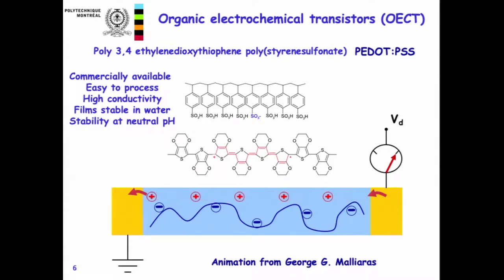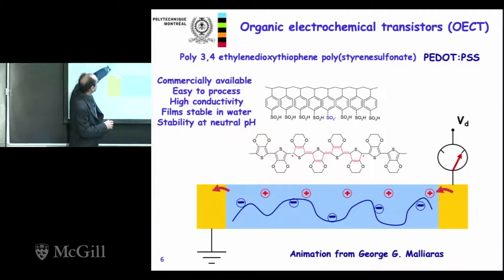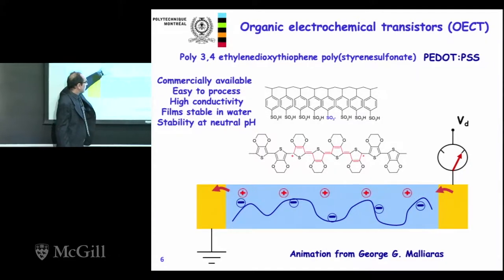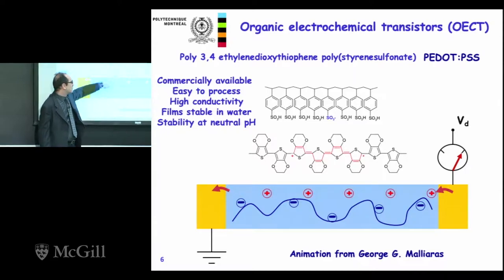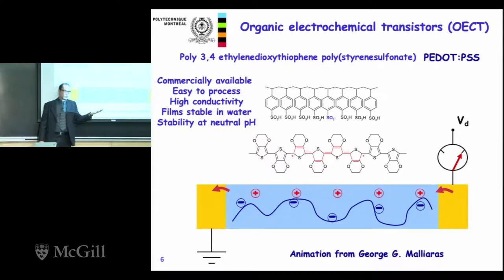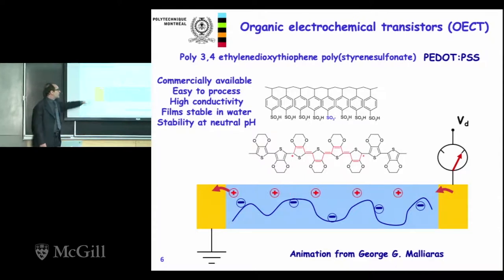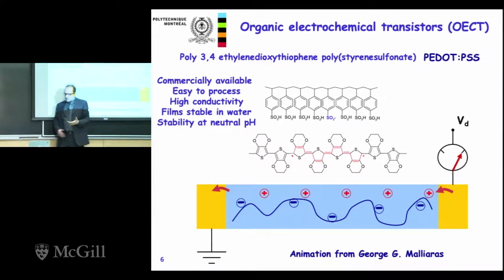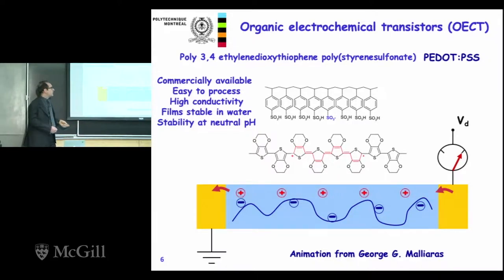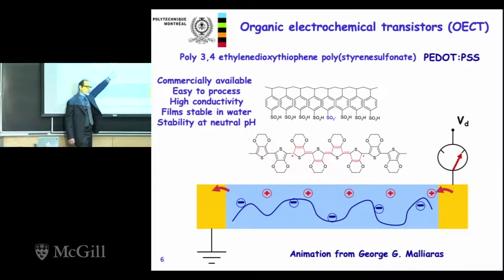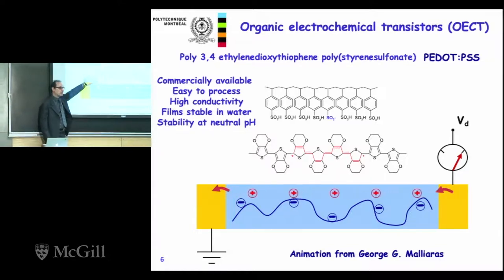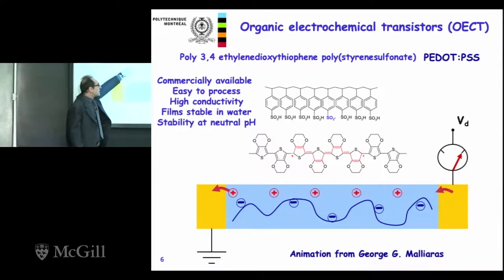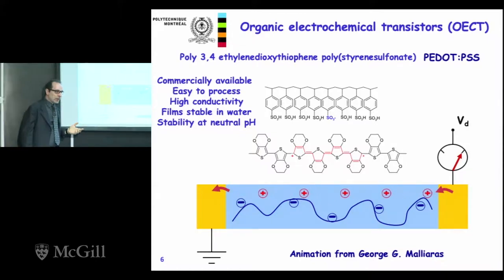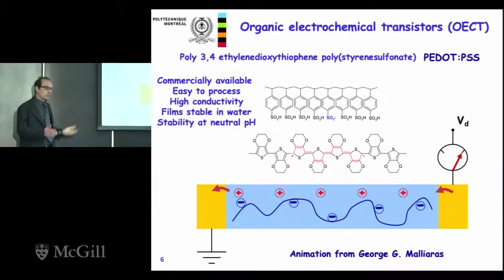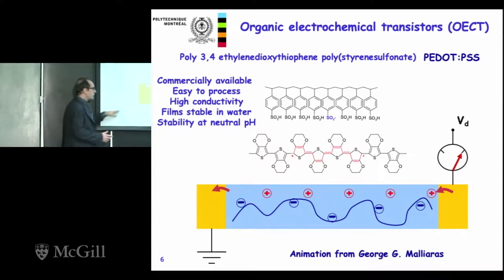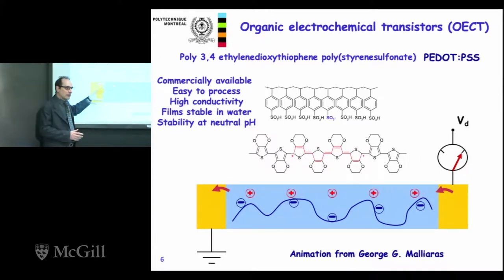Here is also the structure of the material I mostly use in my research, which is called PEDOT:PSS, meaning poly-3,4-ethylenedioxythiophene doped with polystyrene sulfonate. This is the conducting polymer itself. You see the conjugated structure, so an alternation of double and single bonds, without which you cannot have any conductivity. This conjugated structure is essential in any organic semiconductor, otherwise there is no conduction. To increase the conductivity, we have this so-called chemical dopant, which is an ion, a polyanion in this case, a negatively charged species. The presence of this dopant makes this material highly conductive, an efficient hole conductor, so it conducts electron deficiencies.